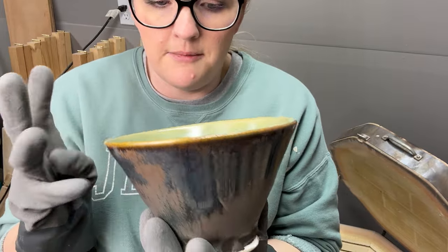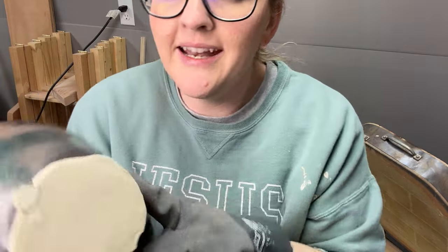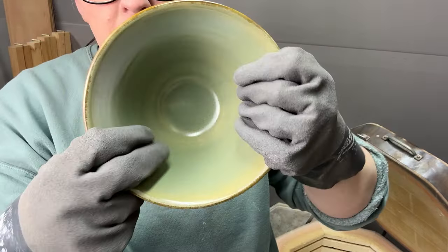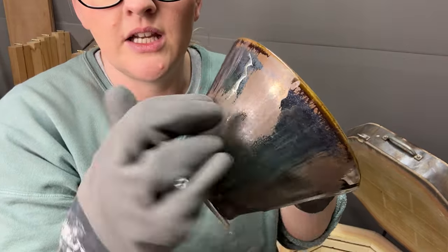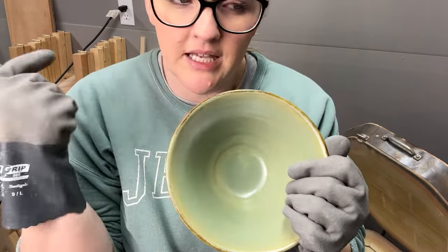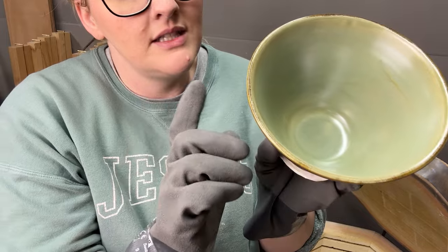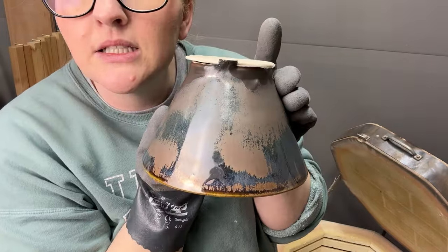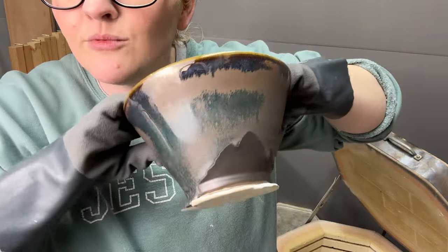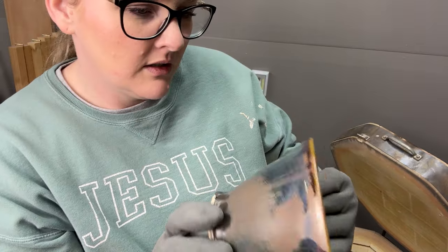This is a re-fire. I did Mako's Black Walnut, three coats all over the outside, and then three coats of green tea on the inside and out. I didn't like the effect it got — it was splotchy on the inside; if you go back to my last video you'll see that. So I added one more coat of green tea, one inside and one out, and it ran quite a bit. The kiln also got a little bit hotter, which aided in that. It doesn't look anything like the swatch on the Mako site, but it's pretty — kind of cool.